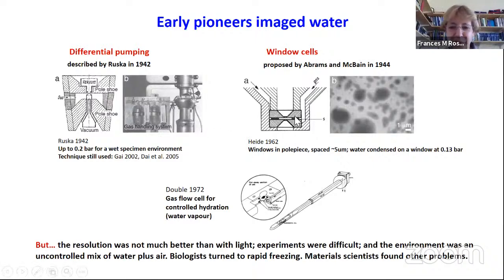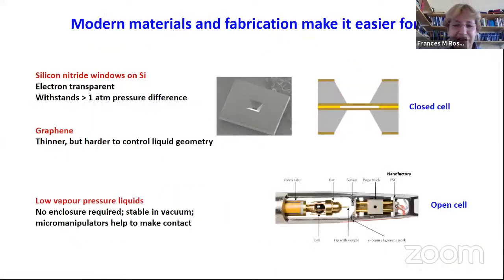The other way, window cells, also proposed in the 40s: you put your liquid in between two windows, a few microns apart. The water condenses. The trouble they had was, what would we make the windows out of? Without modern materials techniques, they were made of uncontrolled thick materials. They weren't very good. And so the resolution was poor, not much better than using a light microscope, and the environment was an uncontrolled mix of water and air. So the biologists turned away from this and developed cryomicroscopy, and the material scientists found other problems to address, until modern materials and fabrication techniques changed the game for us material scientists.